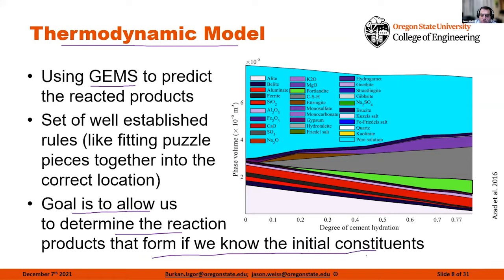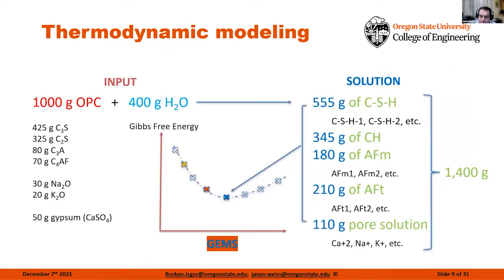So if we know the possible reactions that can happen, we can determine the reaction products simply by knowing the initial constituents. So if we look at this diagram on our right-hand side, we can look at these phases down here toward the bottom of this graph, the red, the black, and the grayish phases. These are all the cement that we have in the system. These are our alites, our belites, our aluminates in the system. The aqua color is the water that we have in the system. And if we bring the cement and the water together, we're going to start to form these reaction products. We're going to form calcium silicate hydrate, we're going to form calcium hydroxide, and we're going to form some of the other secondary and tertiary types of reactions that are going on.